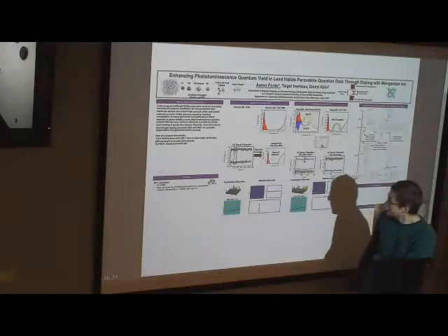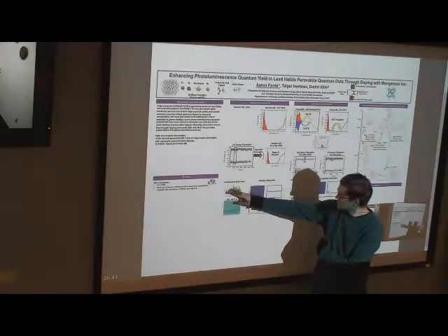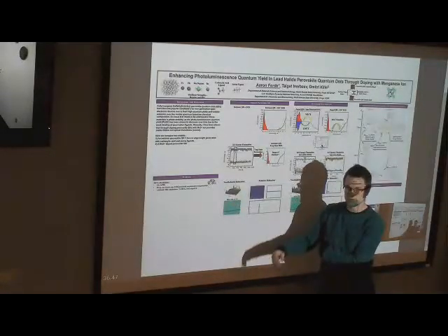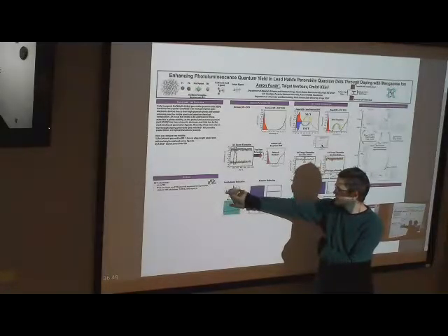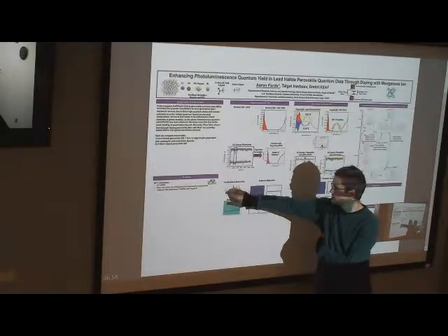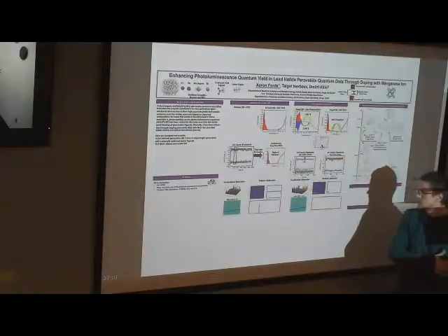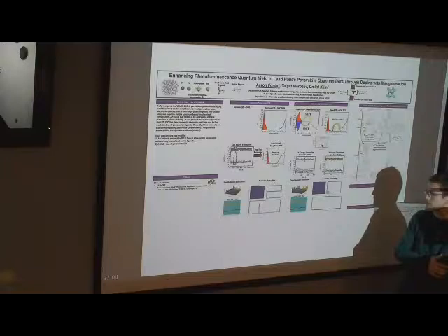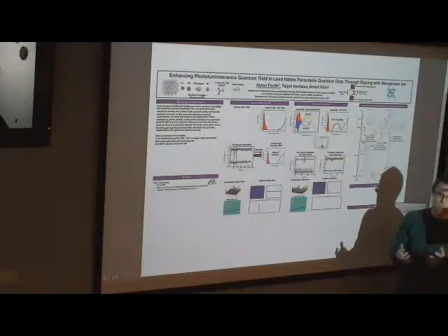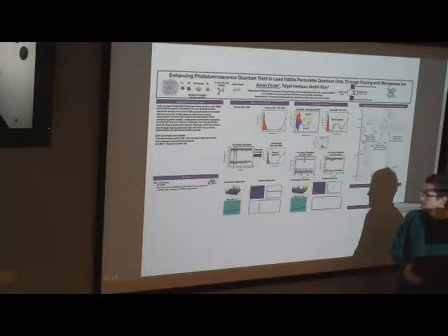We could see that usually it's actually the reverse. For typical systems, like bulk systems, you would see high peaks near the very low end of the valence band and the high end of the conduction band, and then as you get towards the band gap, there would be a slower relaxation. But here we see a kind of reverse trend, which is interesting. That's probably just due to the confinement of the quantum dot, because the orbitals are squeezed together, so there's going to be higher overlap between them, so there's going to be higher non-radiative relaxation that goes with them.